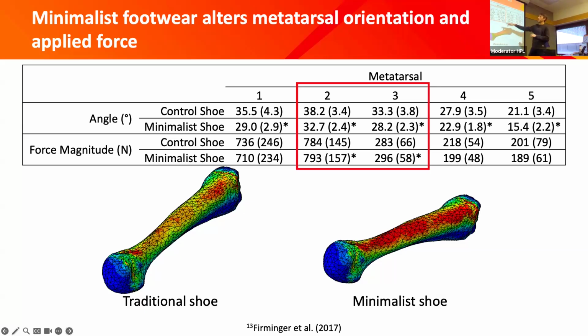So if we now look at the peak force magnitude applied to the bone, in the control shoe, it was about 784. For the second metatarsal, that went significantly higher to 793. And the third metatarsal went from 283 to 296, also a significant increase. So we had 2 things happening here in this minimalist shoe. We had the bone sitting flatter, or in a different orientation, and increased load applied to it. And those paired together to create this perfect storm for increased strain on the bone.